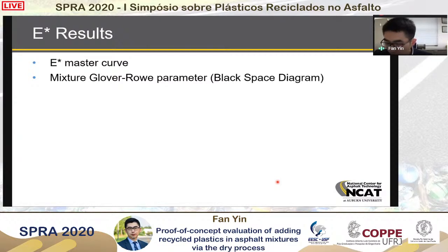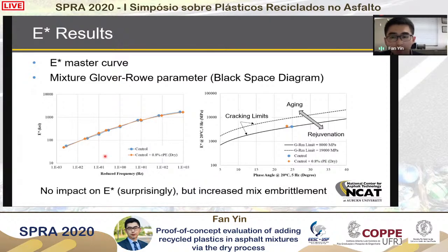When we look at the dynamic modulus test, we look at the E-star master curve, and we also look at the Glover-Rowe parameter when plotted on the black space diagram. In this case, adding the plastic did not change the stiffness of the mix, which is also surprising to me, given the Hamburg data we showed before. But when we just look at the master curve, one thing we were not able to capture is the phase angle. But when we look at the data on the black space, it gives us a better indication of the mix behavior. So this is very similar to the way we look at the binder Glover-Rowe parameter. We have stiffness on the y-axis and the phase angle on the horizontal axis.